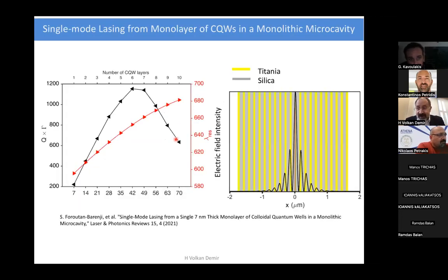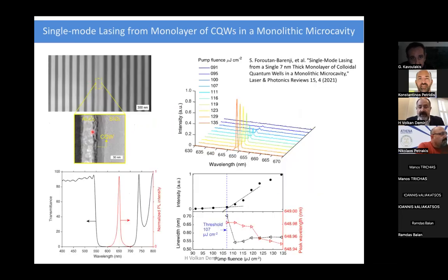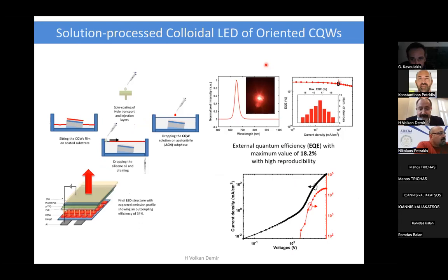An easy way to further push this, possibly using only 1 monolayer, is to have an even better cavity structure. This is very simple, again, a pair of Bragg reflectors where we sandwich a single monolayer. And this structure then allowed us to observe single-mode lasing from a single monolayer, which is just 7 nanometers thick. This, to the best of our knowledge, appears to be the thinnest colloidal gain medium at the moment to observe gain.